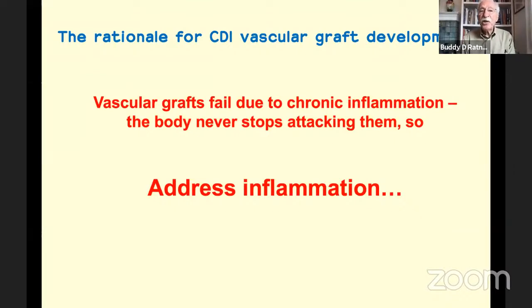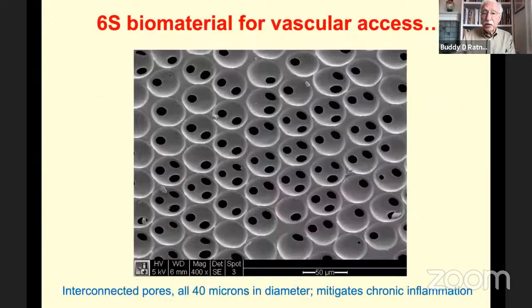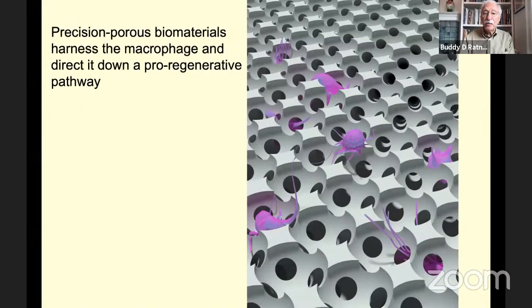So our rationale for the Center for Dialysis Innovation Vascular Graft Development is we feel that vascular grafts' 50% failure rate is due to chronic inflammation. It really is quite evident the body never stops attacking them. So we address inflammation. And we developed a class of materials in our group at the University of Washington. We call them 6S. I won't go into the details, but these are materials where all pores are 40 microns in diameter. Pores are interconnected. And we found in many experiments that they mitigate chronic inflammation.